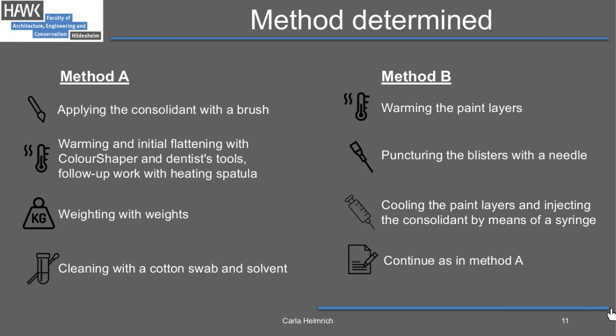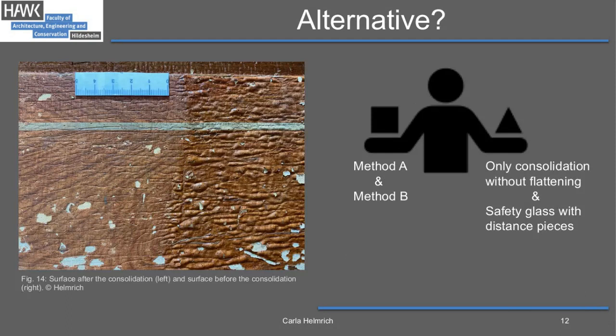When laying down the heat blisters, a slight cratering and wiggling of the paint will occur, especially in areas with large blisters. As you can see here on the left, this part is consolidated and flattened. This is because of the strong expansion of the voluminous blisters with a simultaneously constant carrier size. So the surface of the blisters expanded while the carrier was staying the same.